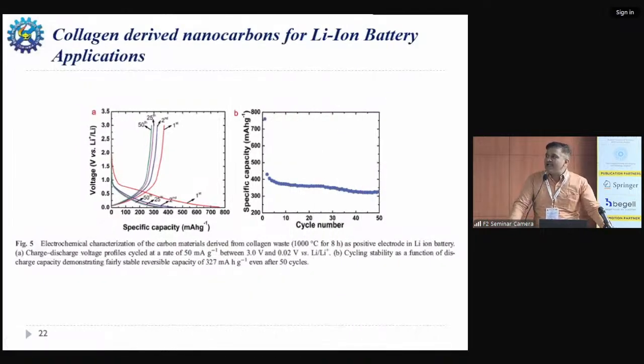So we also tried to use this for lithium battery applications, where we used this carbon as an anode material, and we observed very good cycling capacity, even up to 50 or 60 cycles.